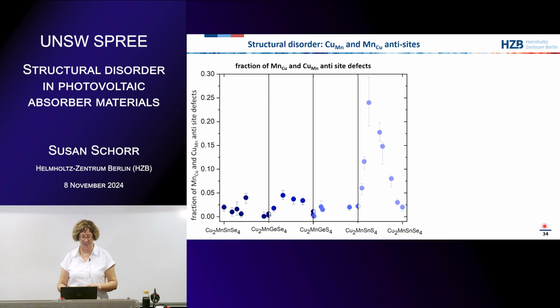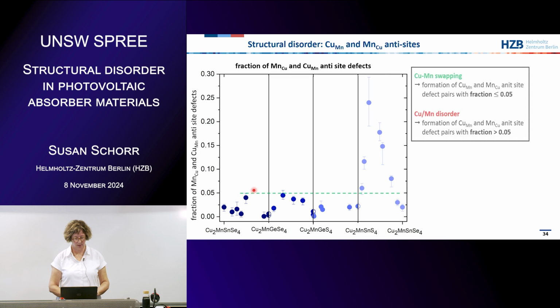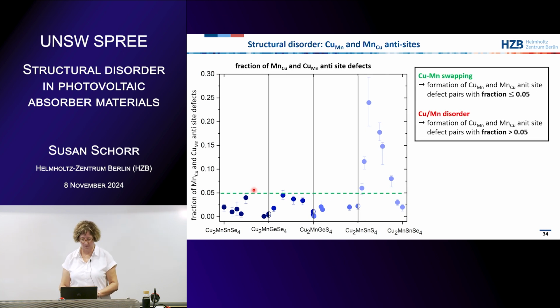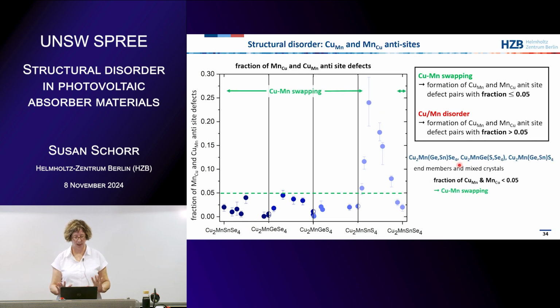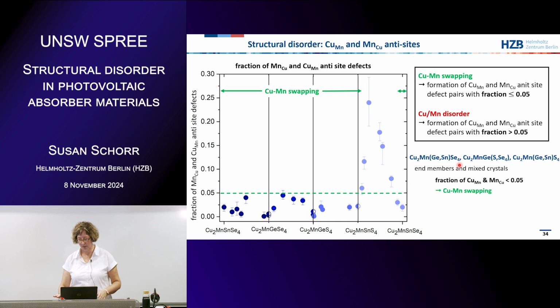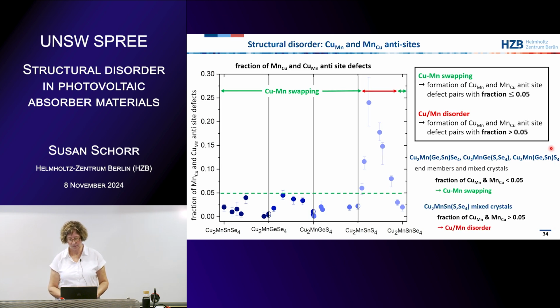And now in this series where we alloy cations and anions, we see this is the fraction. It's mainly below 5%. There is one exception if we mix copper manganese tin sulfide and copper manganese tin selenide. Then we have an increase of copper on manganese and manganese on copper antisites. It can go up to 25%. So that's why we say that we have copper manganese swapping mainly in these mixed crystals, but also a little bit of copper manganese disorder, but only in the copper manganese tin sulfide selenide mixed crystals.